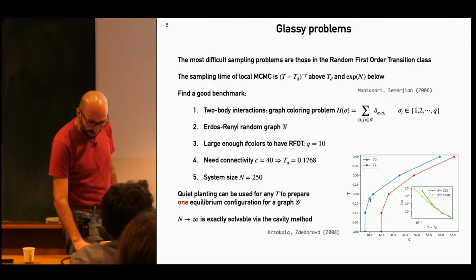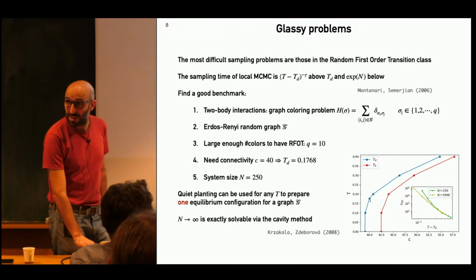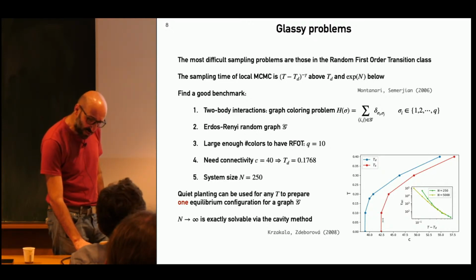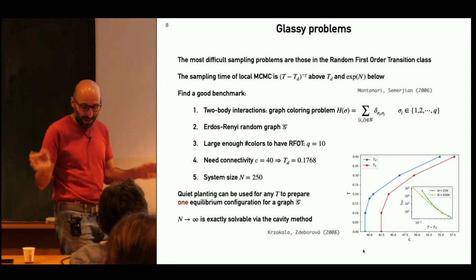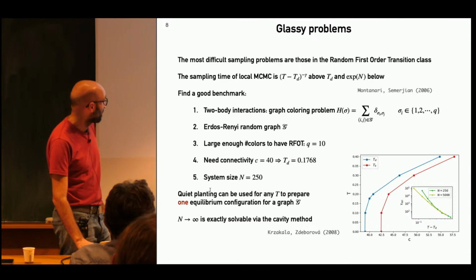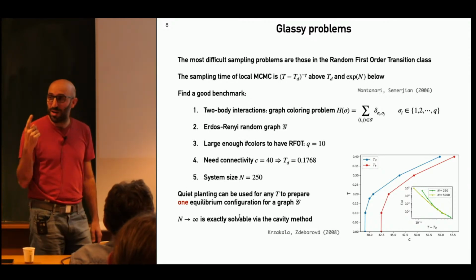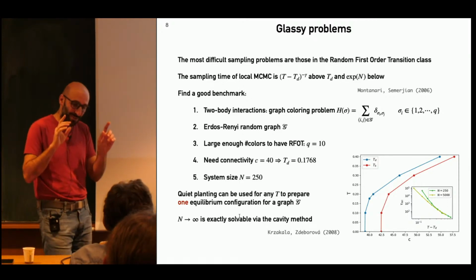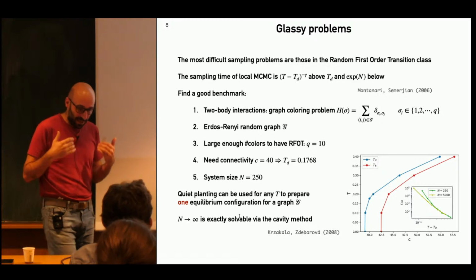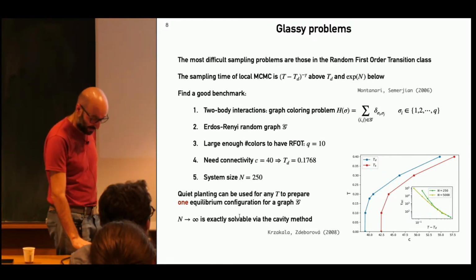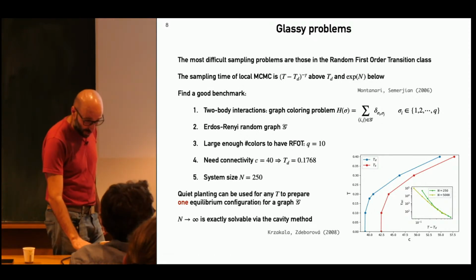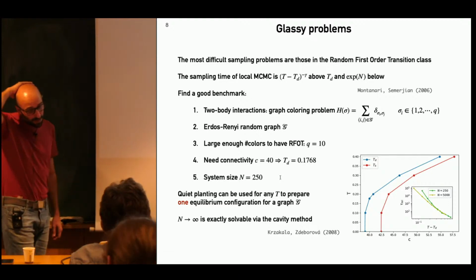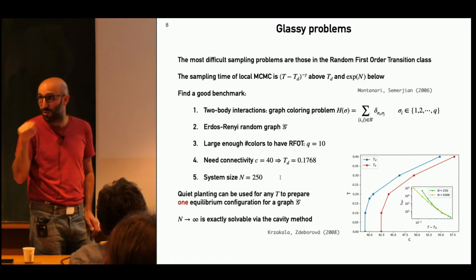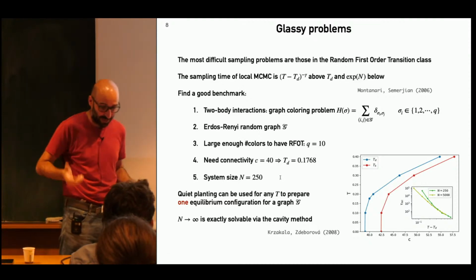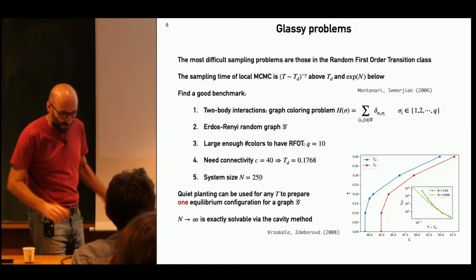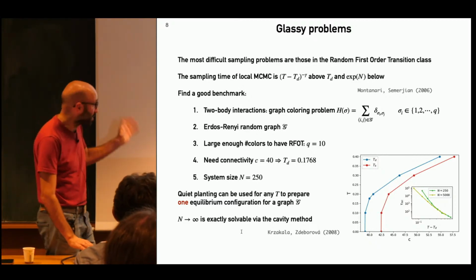For connectivity 40, we have a dynamical transition at temperature 0.17. Below that temperature, it's exponentially hard to sample in N. And there is no Kauzmann transition, which is good, because, this is technical and I'm happy to discuss it later, it means we can use a technique called quiet planting that allows us to generate one equilibrium configuration for the graph. So given a graph, we have one equilibrium configuration that we can use to start the local Monte Carlo and to check the equilibrium local Monte Carlo dynamics. The system size is 250. We needed a large enough system size because the connectivity is 40. To not be so far away from the thermodynamic limit, we wanted the system big enough, but we couldn't make it much bigger because then it becomes too hard. So this was a good compromise.